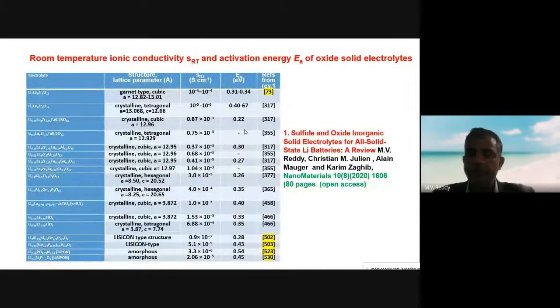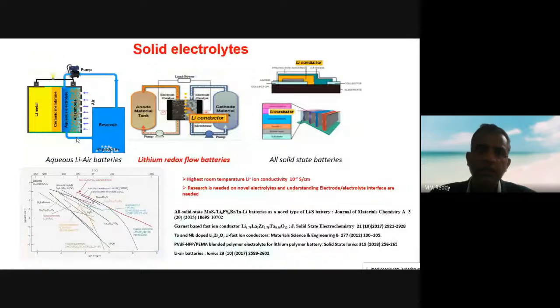For example, sulfides have good conductivity. But if you expose them to moisture, they become hygroscopic, become smelly, and sometimes have material stability issues. Oxide seems to be good, but if you want to make a good ceramic membrane, we need high temperature, etc. So if you want to use the ceramic membranes, these electrodes protect the solid electrolyte. So remember, these are all the different applications of the electrolyte, for example, redox flow or all solid state battery, etc.